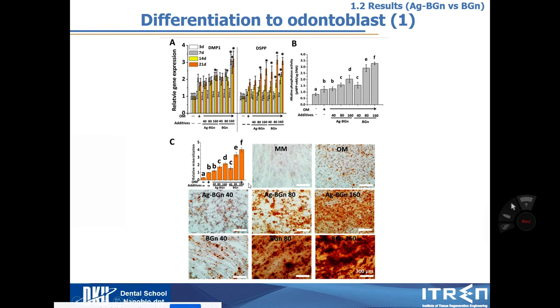And then same as before, I checked their gene expression levels, DMP1 and DSPP. As you can see, the silver BGN shows a similar or slightly smaller increase of gene expression for odontoblast differentiation compared to normal BGN, because this is, I feel, a drawback of silver. So when you look at AGBGN and BGN, BGN is a little bit higher than AGBGN. Also this DSPP, we can see like that.